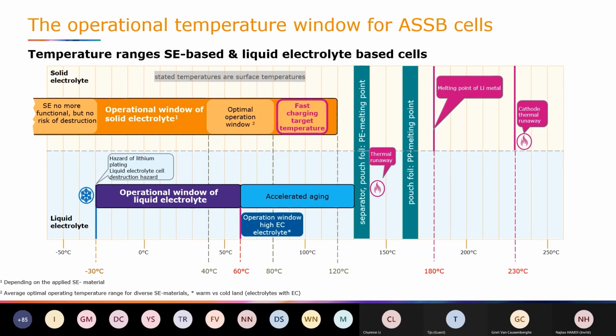Last but not least, we will compare the operating temperature windows. As you can see, the conventional cells operate in a window between -30 degrees Celsius and around 60 degrees Celsius. If you go beyond this temperature limit, you will face first an accelerated aging, and above 120 to 130 degrees Celsius, you run into a thermal runaway. The separator is melting and the thermal event will start.